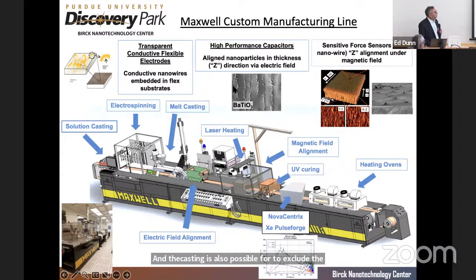And the solution processing can also involve a unique characteristic of this machine, that you can apply an electric field to organize particles that are dispersed in the polymer precursor. So with the same concentration of, for example, barium titanate, you essentially double the dielectric constant of the material without having to increase the concentration. This is also a demonstration of micro-computed tomography, where the nickel nanoparticles are organized with a 2.7 Tesla magnet into columns, essentially nanoparticle columns that are separated by dielectric. That's useful for piezoresistive sensors for very low cost sensors. They have extreme anisotropies, very high conductivity in the thickness direction, and no conductivity in the plane.